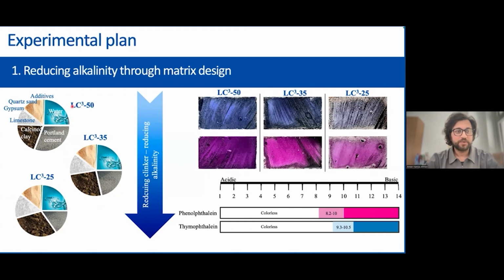Essentially, what we are doing is cutting clinker content from 50% in LC350 to LC335, where the clinker content is 35%, and in the last we use only 25% Portland cement. The remaining portions we replace with calcined clay and limestone at a constant ratio of 2:1 by weight of binder. And to make these matrices for SHCC, we of course add quartz sand and some admixtures for tuning the workability.